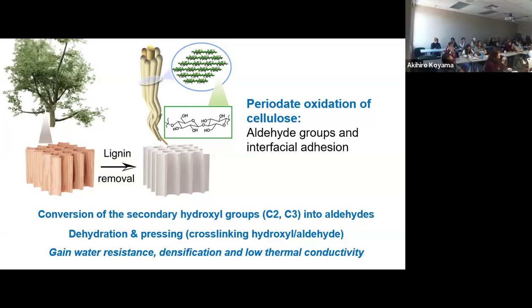We take wood, we remove lignin, and then we do periodate oxidation of the material that is left. Here, essentially, what you have is replacement of OH groups by aldehyde groups. Those groups are reactive. They can find each other and cross-link. Then you get a material that can densify and become strongly bonded together. So that's the whole thing. We use a little bit of chemistry and colloid science, surfaces, to then make a material that is transparent. So that's what we did here.